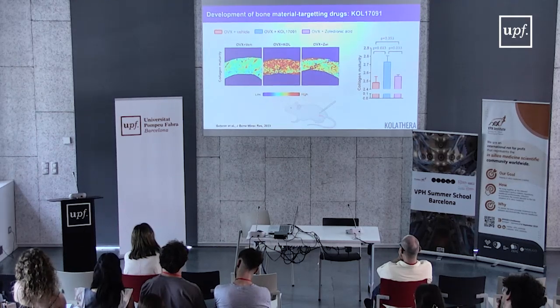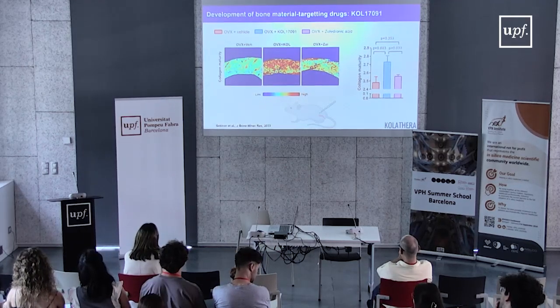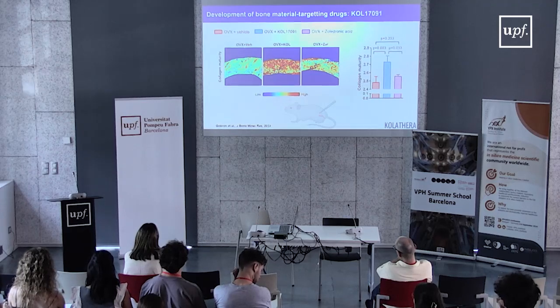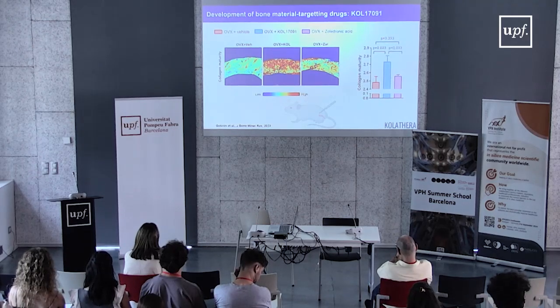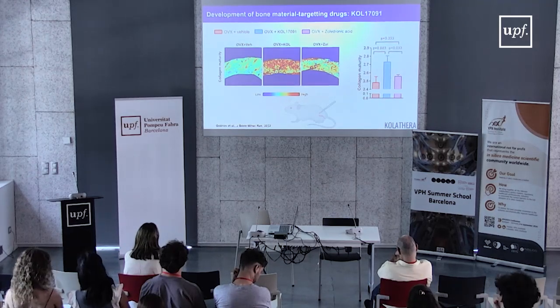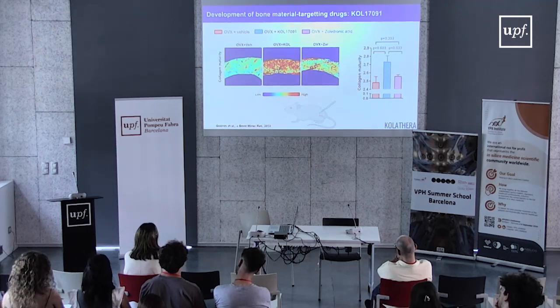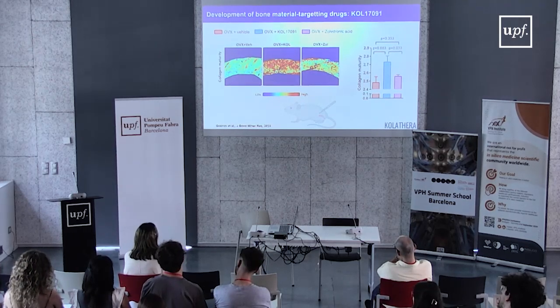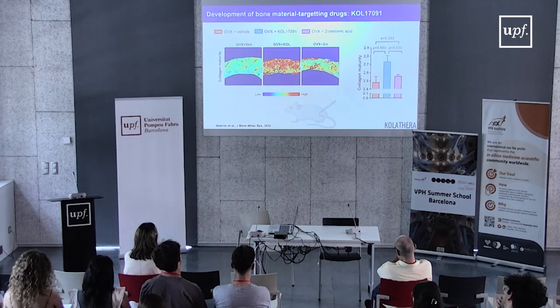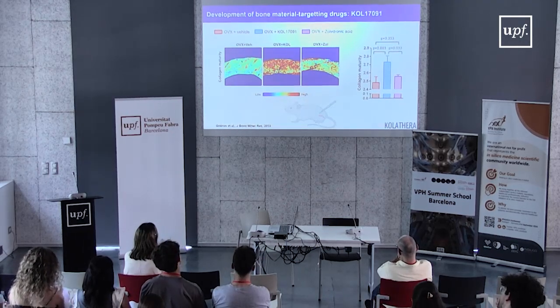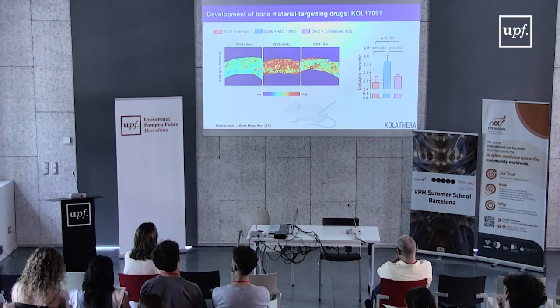So if we look at the amount of collagen maturity, you can see that we're quite low in the OVX animals treated with a placebo. If we put bisphosphonate, we don't do much on the collagen maturity. But if we put KOL17091, we actually increase the collagen maturity greatly. And if we quantify it, we increase the quality of the collagen matrix by 12%.